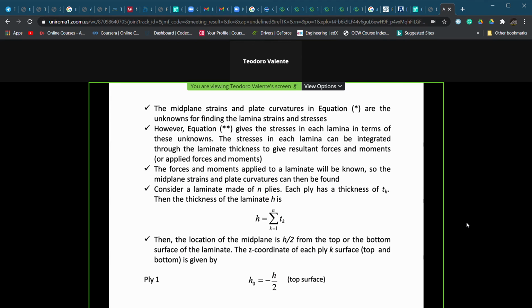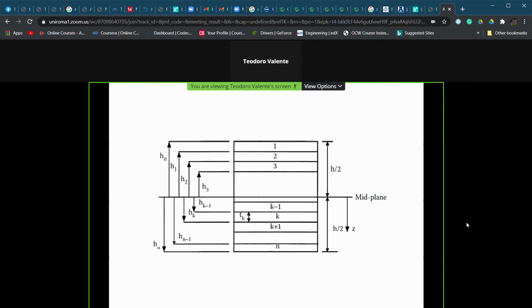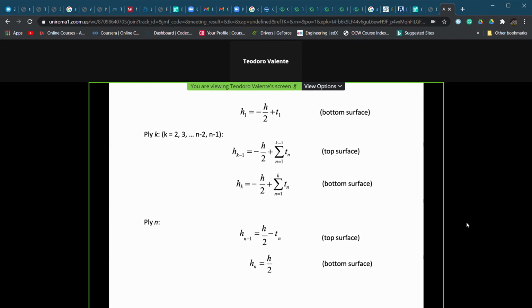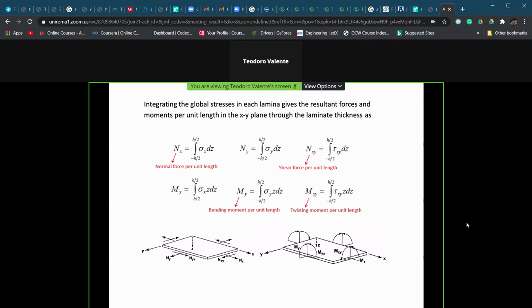Then, again, a recall, we can introduce this model, for example, which was explained in the previous slide. We refer to the mid-plane, because we are usually using symmetric disposition of the layers, and can have, by using the macromechanical approach, an estimation of a strain distribution in the case of elastic behavior of our system, and in the case in which inside each lamina we can make the assumption, that's the simplified approach, of a plane stress state for the evaluation of the distribution of stress and strain in the single ply. Then that's normal, you know that one.